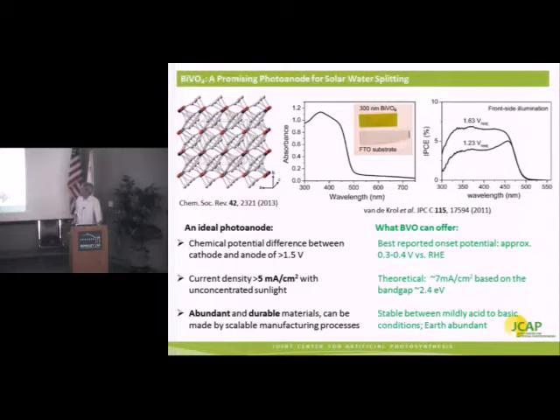For an ideal photoanode, you would like to have a current density greater than 5 milliamps per square centimeter. Based on the band gap of bismuth vanadate of 2.4 electron volts, it's got a theoretical efficiency limit, or a theoretical maximum current density of 7 milliamps per square centimeter. Now, right now, that's not achieved whatsoever because we have problems with charge carrier transport in the material. But current densities between 1 and 3 milliamps per square centimeter are routinely achieved with this material. By improved materials design, materials synthesis, we should be able to get much closer to the 7 milliamps per square centimeter. Finally, this material is abundant and durable. Bismuth, vanadium, and oxygen are not rare materials. So it fits the requirement in the JCAP mission of being an earth-abundant system that's scalable and manufacturable. And the system, bismuth vanadate is stable between mildly acidic to quite basic conditions.